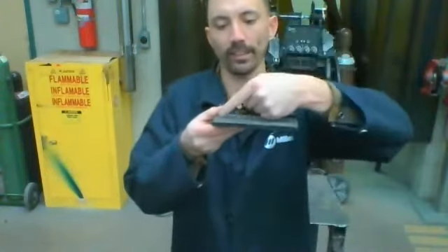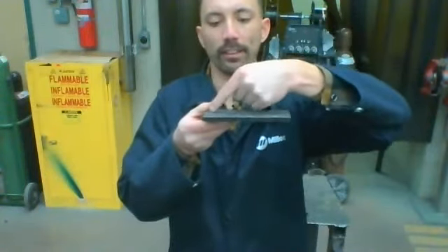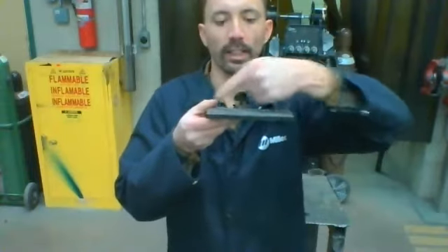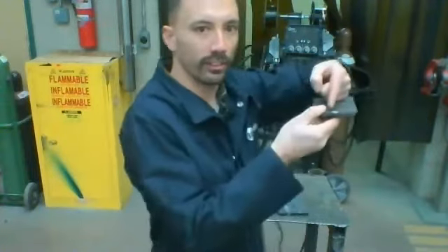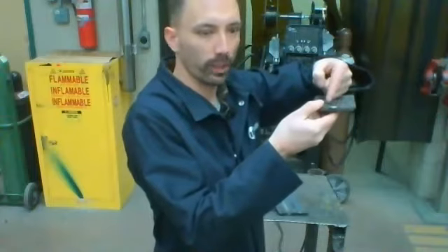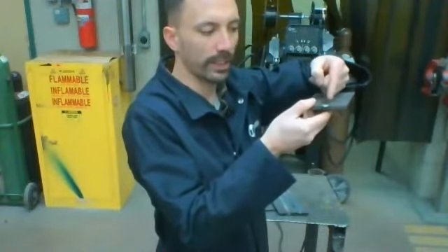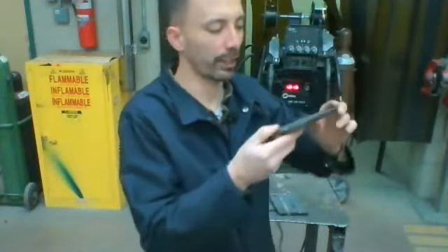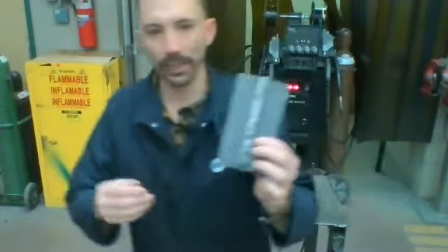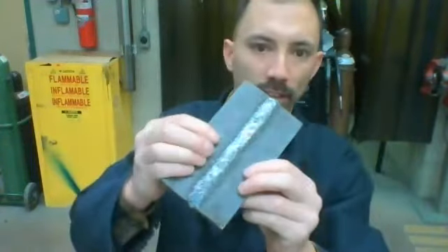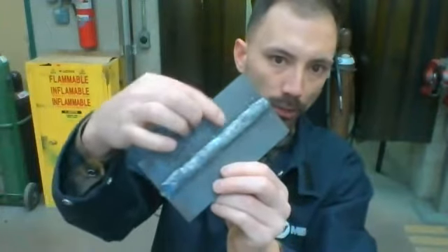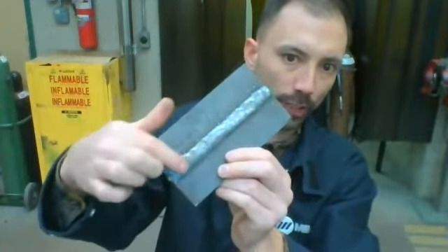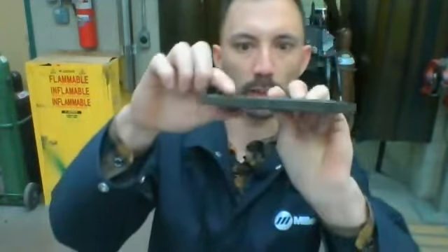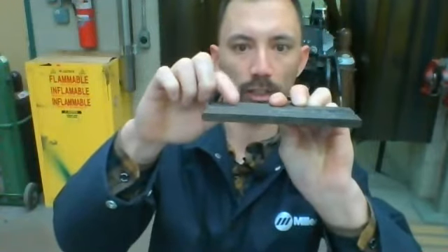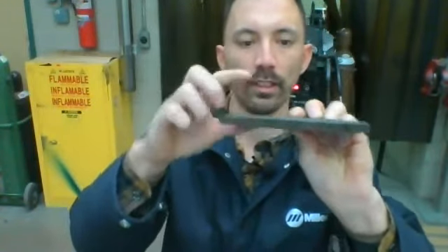So I had my nozzle pointed in here. I was pulling this way. I was just giving a slight little side-to-side wobble with my wire, taking my puddle left and right. And doing that gave me this one-pass cap. I was able to get the puddle wide enough to fill that groove, just put a little bit of reinforcement on it, which is what we want, just slightly above surface. And that was done in one pass.